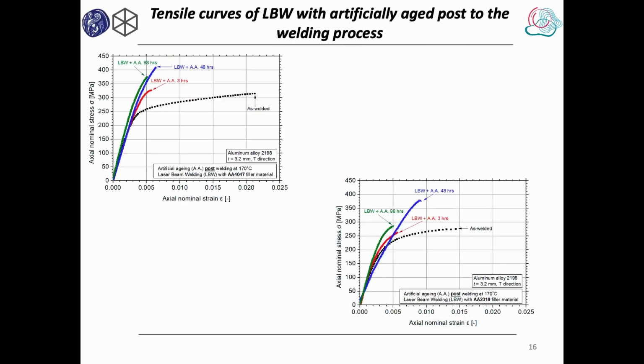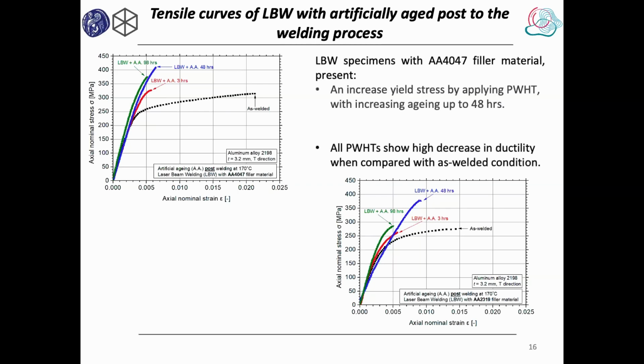And we also investigated the effect of post-weld heat treatment on the mechanical properties. We see that in the as-welded condition, we have a reduced level of yield strength. And if we apply post-weld heat treatment, we can somehow increase the yield strength and mechanical performance of the joint. And we investigated this for two conditions.